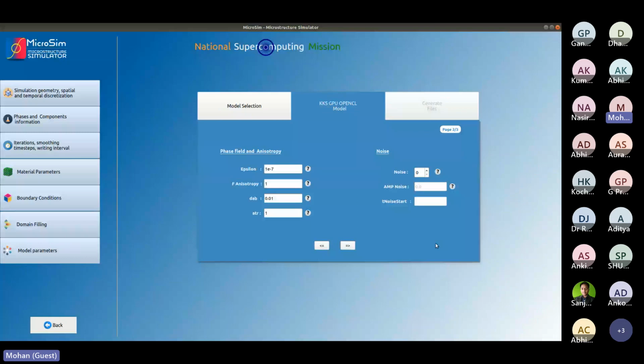In this case of solidification, the dendrite morphology is mainly characterized by dendrite tip radius and the velocity. So you want to resolve the tip radius as much as possible to capture the physics. But if you start resolving with more number of points, we lose the generality of the diffuse interface width, and also you will need to access more computational power. So you have to make a balance based upon the model and your microstructure. Choose the number of points or interface width which still captures your characteristic length scale and give that information appropriately. That is the only parameter which you give. The rest are the material parameters we have given or the numerical parameters. This is the model parameter.